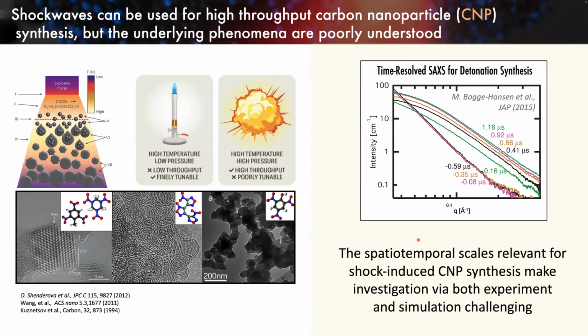These are time-resolved small angle X-ray scattering data monitoring detonation-induced nanocarbon synthesis. You see these curves before the experiment takes place that are linear, indicating there are no condensates present in your system. Then you instantaneously transition to this regime where there's a knee in the data indicating the condensates have already formed. So from this sort of measurement, really all you're getting is an upper bound timescale for formation - not detailed kinetics or underlying mechanisms.